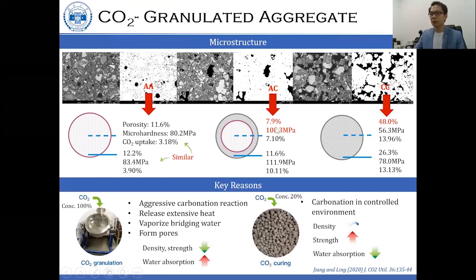So the key reason is because during the granulation, we apply 100% concentration of CO2. And we are also using the very reactive material, BOFS, for the production process. So the aggressive carbonation reaction is taking place and releases extensive heat and vaporizes bridging water to create the pores. However, this situation might not be similar if we are using a low CO2 reactive material instead of BOFS slag. And for the CO2 applied after the granulation, or CO2 curing, it is very beneficial for the strength development, and we can reduce the water absorption.